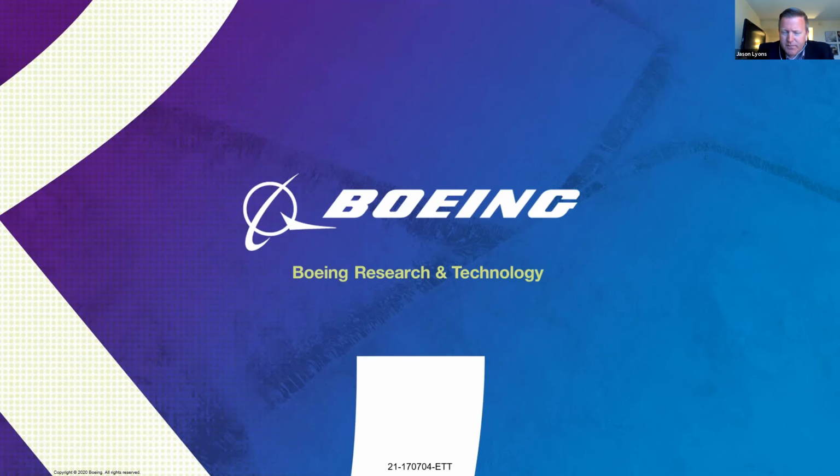Okay, and this is a play off of that: how do you feel about chemical bonding? The example that was given was PBT to PET and PC, PBT PET to PC. Sorry. Chemical bonding. So the primary concern that I have with chemical bonding is that if the application is not very precise and closely monitored, you can have degradation of the thermoplastic. That's something that we have looked into within Boeing. We've found that it's not really desirable because we have had a lot of issues with thermoplastic cracking or crazing, and in particular crazing along decorative surfaces where you essentially destroy that decorative aesthetic, that appearance item that you're looking for.